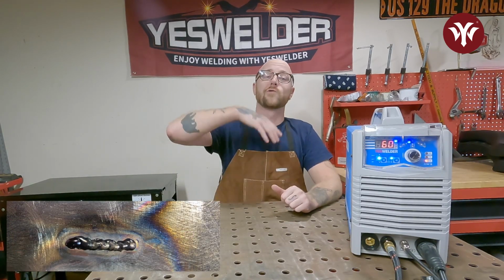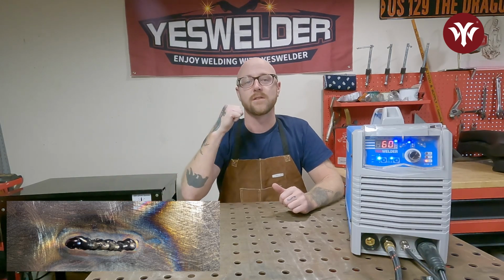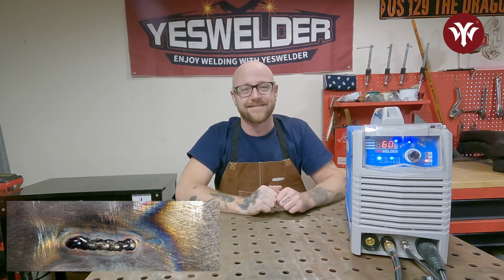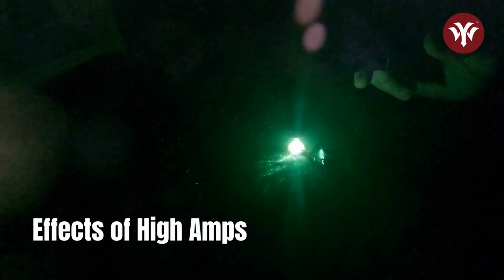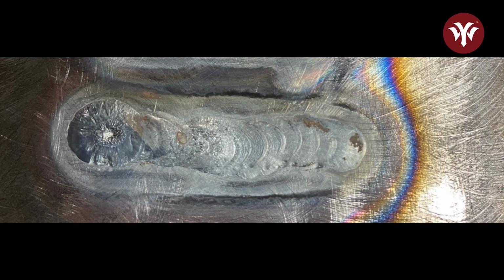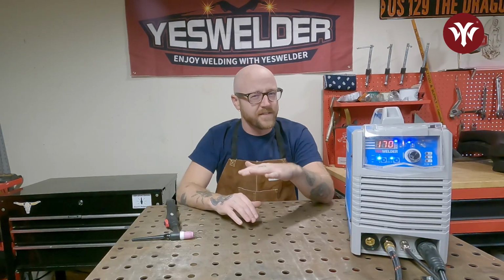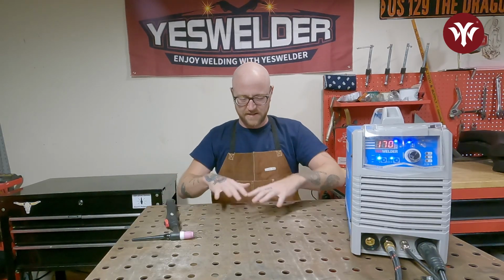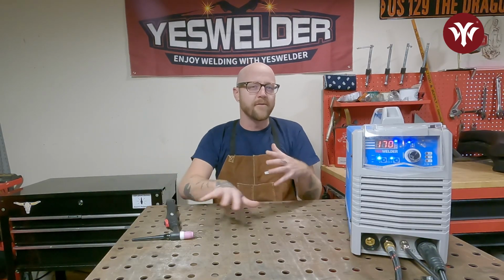So let's turn it too far up and let's see what it looks like when you're running too many amps. So as you can see there, the puddle is erratic. You start the machine, we have it set at 170, which is way over that one amp per thousandth rule. And you start it and the puddle just immediately washes out. You have very little control. It's very wide, it's very flat. And when you're adding rod, it's just dissipating and kind of pooling everywhere.